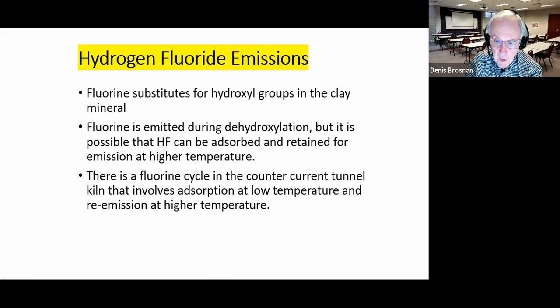Well, when you fire the clay and go through dehydroxylation, and the hydroxyls come out, if fluorine is present, it's going to come out too as a fluorine F- ion. But it can't stick around as fluorine very often because fluorine is so reactive, so it grabs the hydrogen from somewhere and becomes a molecule of hydrogen fluoride in the kiln exhaust. So first of all, you're going to have dehydroxylation temperatures in order for the fluorine to be released.